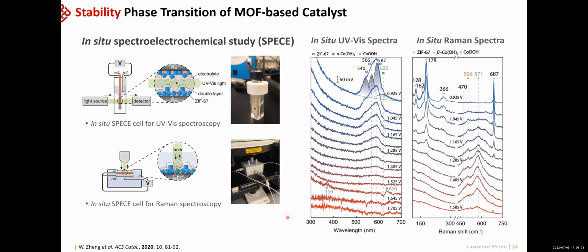So from the result, first from the UV-Vis, at the initial or at the low overpotential, we still see the signature peaks from the MOF, ZIF-67. But you can see that with the increasing potential, their signature peak disappears quickly, which means they're getting destructed. Instead, we start to see alpha cobalt hydroxide species appearing, and then they are consumed. And then we start to see 3+ species, which is cobalt oxyhydroxide.